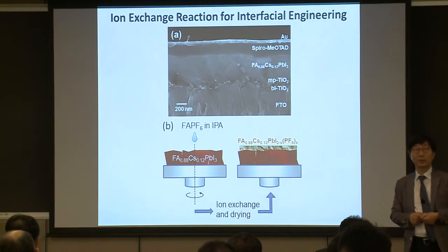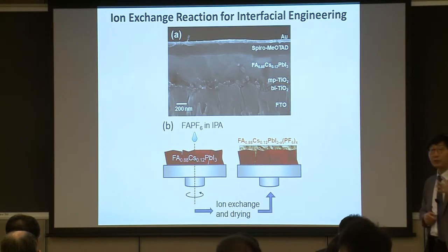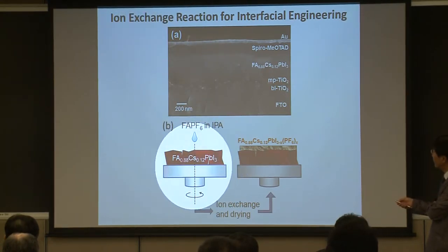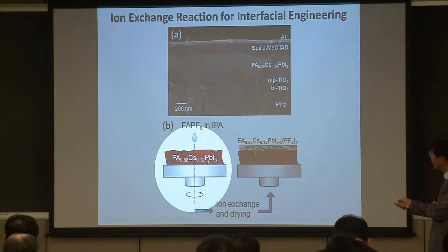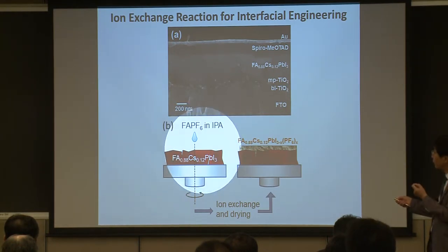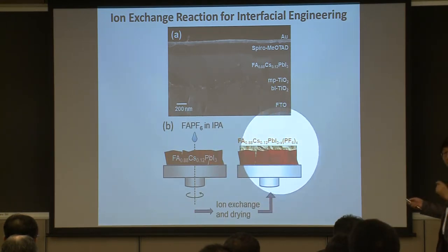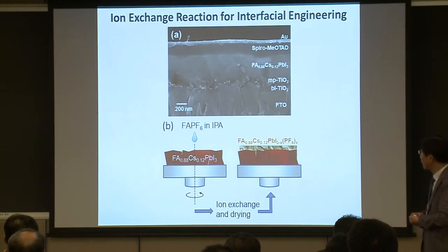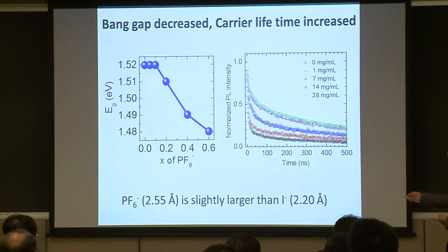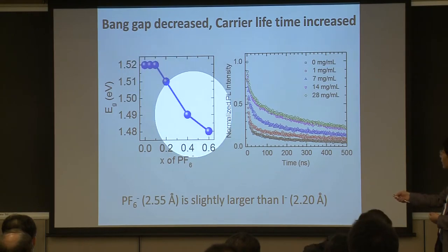And for interfacial engineering, we adapted an ion exchange reaction. Here, first we make the perovskite layer, and then post-treat it with PF6 anion to replace some of the iodide, and then we form the FA PF6, a kind of thin layer on top of the perovskite layer by the ion exchange reaction. And then we found that the band gap energy slightly decreases with increasing PF6 concentration.